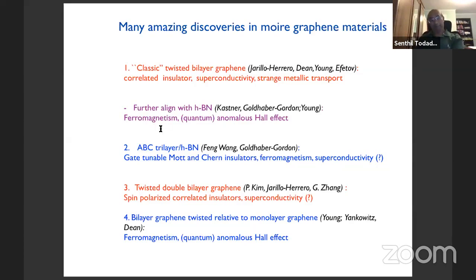It shows ferromagnetism, okay? And it also shows an anomalous Hall effect, which it turns out, at least in some of the experiments, is a quantum anomalous Hall effect. It's a very nice example of a 2D material showing a quantum anomalous Hall effect. Then there's the ABC trilayer graphene system aligned on hBN. Feng Wang's group, sometimes in collaboration with Goldhaber-Gordon, showed that you get gate tunable Mott insulators, so you can tune in and out of the correlated insulator with a gate. You also get Chern insulators in this system, which again you can tune with a gate. You get ferromagnetism. There are even some signatures of superconductivity.